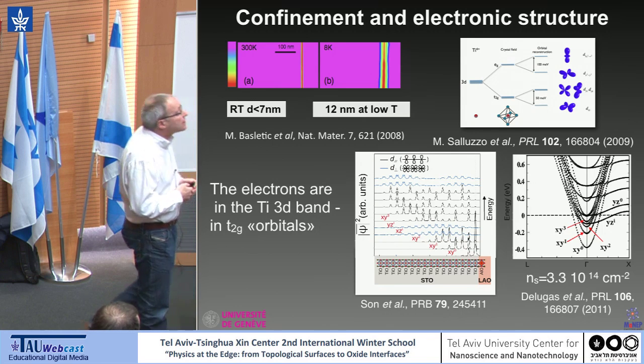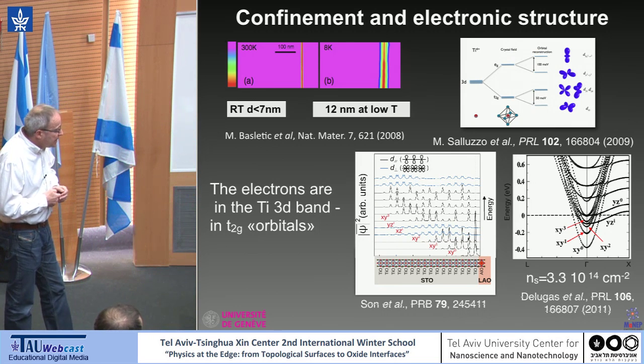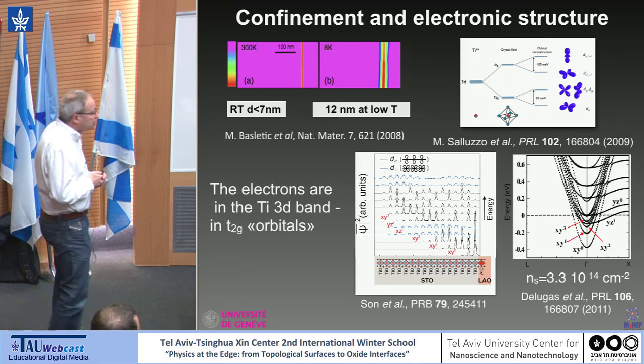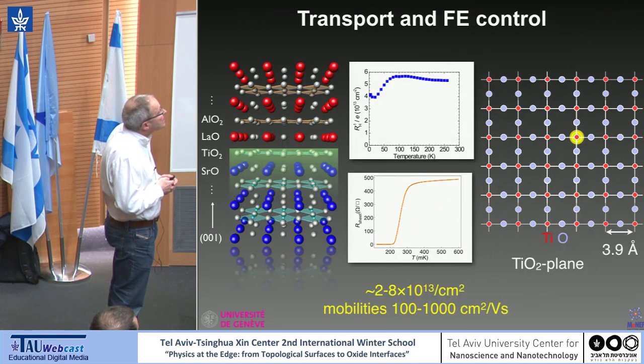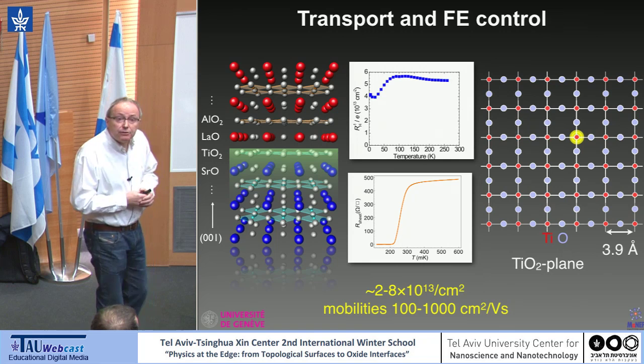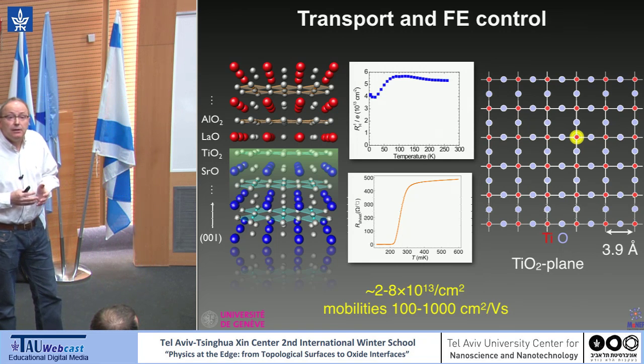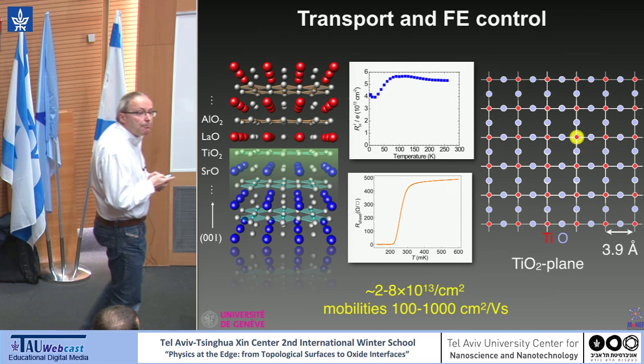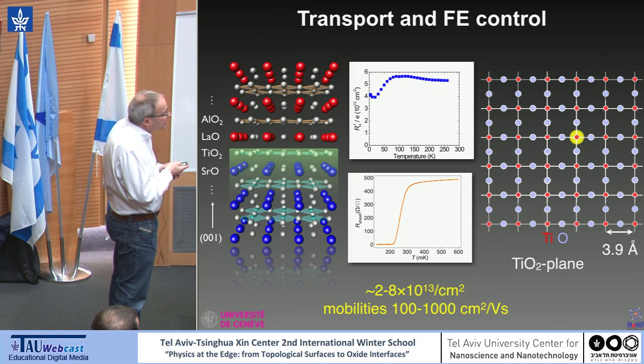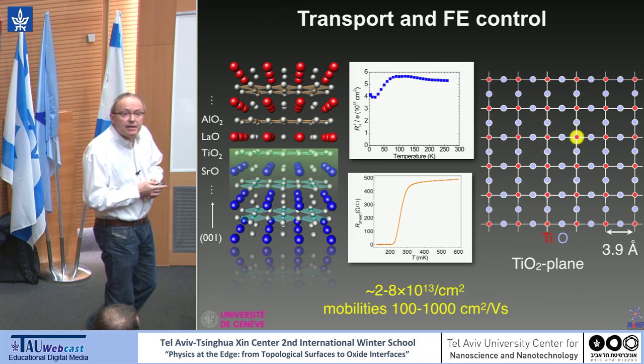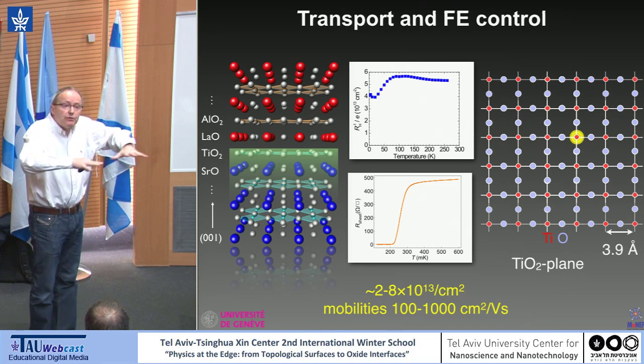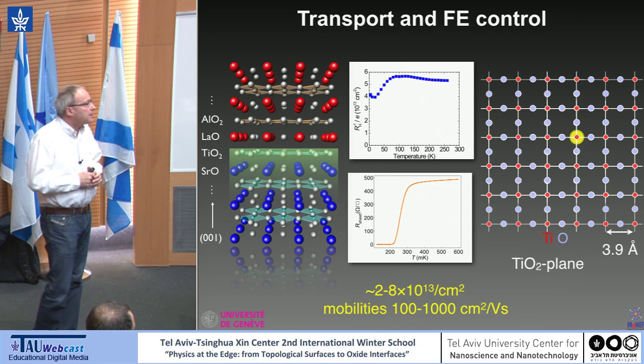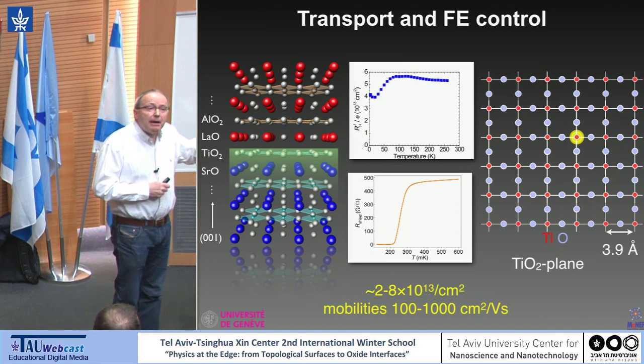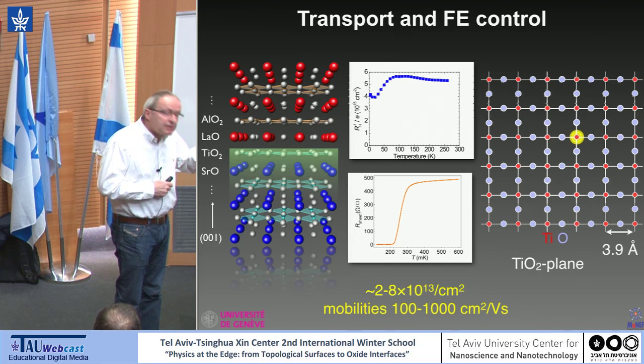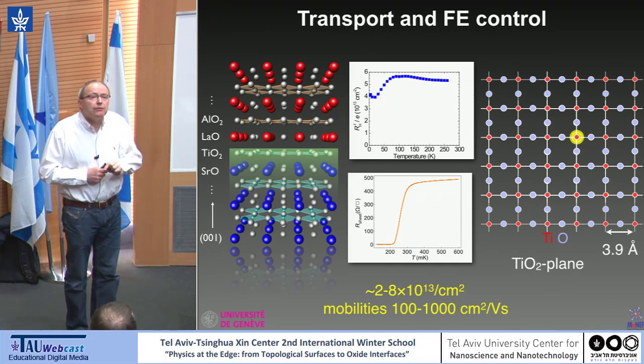It will be important for the discussion of superconductivity. OK, let me move now to transport experiments. So this is your system. I told you it's metallic. If you measure the Hall response and you extract some information on the carrier density, you find that the mobile carrier density is 2 to 8 times 10 to the 13 per square centimeter. Again, what we measure is the sheet carrier density, so the carrier density per square centimeter. Now, maybe you remember that I told you that the polar catastrophe scenario was predicting 3 times 10 to the 14.